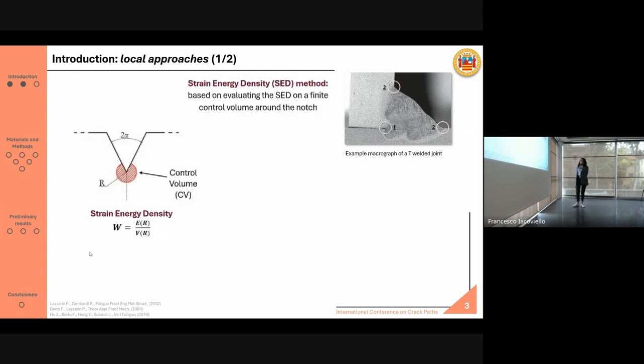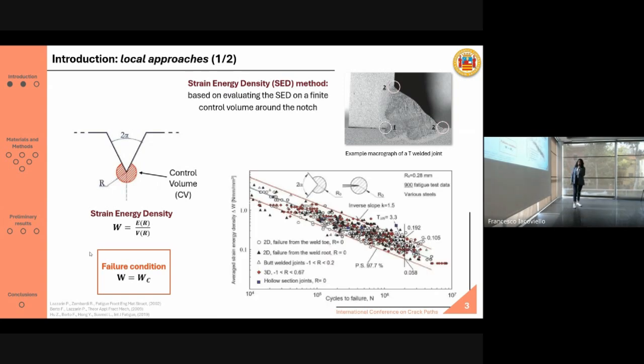Concerning the strain energy density method, we all know that it's based on evaluating the strain energy density in a control volume that is typically cylindrical, surrounding the notch. And we know that the critical failure condition is usually met when the strain energy density equals the critical strain energy density value. And here you can see an example available in literature of hundreds and hundreds of welded joints that were tested.